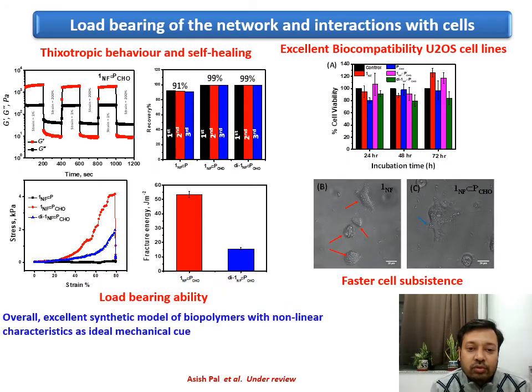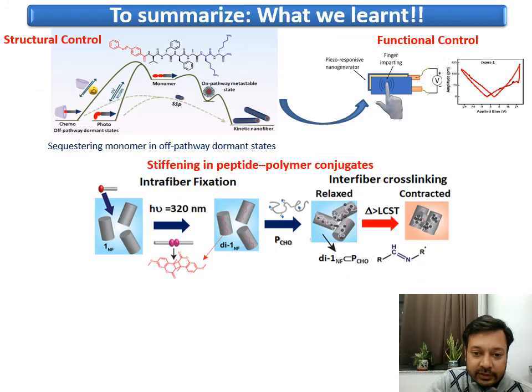We also looked into the load bearing and thixotropic property of our material, and they show excellent thixotropic behavior upon higher stress, and that is a very ideal situation for designing biomaterial. We have looked at some preliminary cell response in U2OS cells, and we did see very faster cell subsistence, and you can see the development of cell fingers in the presence of such nonlinear material as compared to the supramolecular hydrogels.